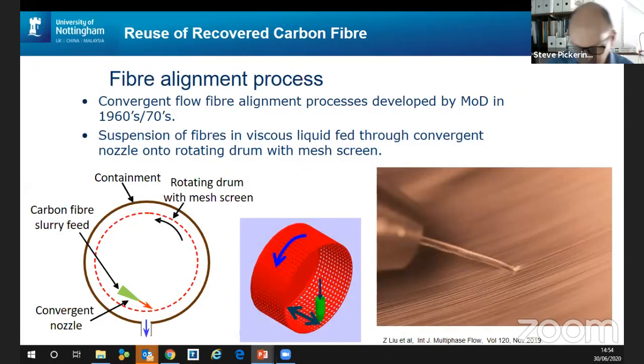So what we need to do is to look at processes for being able to align the fibers, and we've developed a process at Nottingham based on some technology developed a while ago by the MOD, which is to take a suspension of fibers, pass them through a convergent nozzle, and to align them, and then deposit them on a mesh inside a rotating drum. And here's an image of the jet. The fibers are in there, and we're depositing them on the drum.